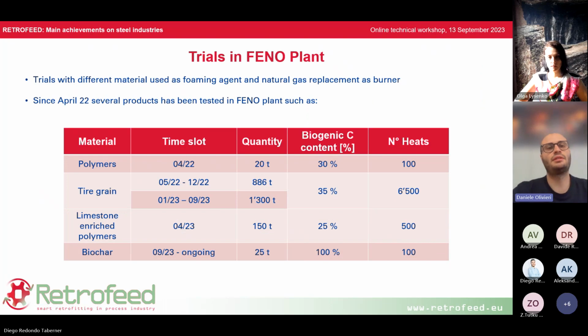Now, these are the materials that we used in this project, and we, of course, tried them both as a replacement for the burner, but also as the foaming agent. These are the main materials that we tried. We tried polymers as the first attempt. The most important thing is that every material has a certain percentage of biogenic carbon content. So with the polymers, we tried to replace, for example, natural gas as burner. Then we had a large number of trials with tire grains as injection in our furnace, and we injected a lot of material, around 2,000 tons.